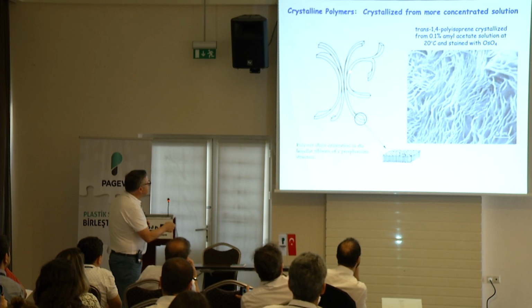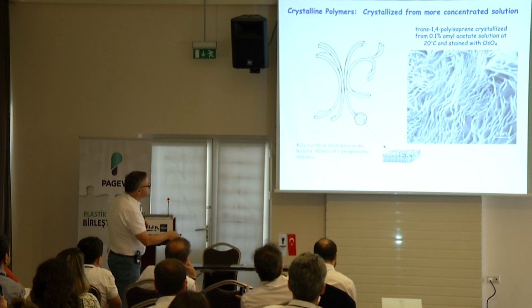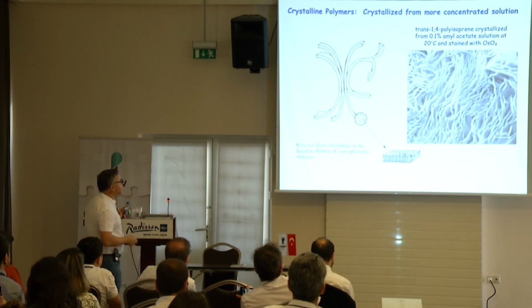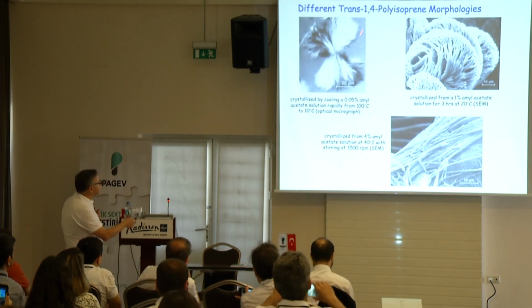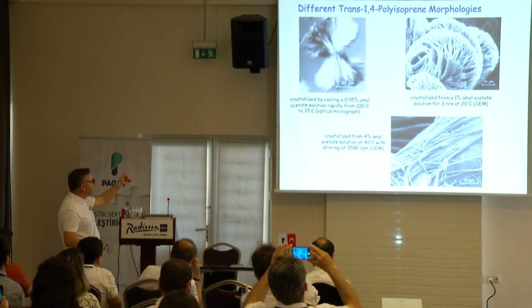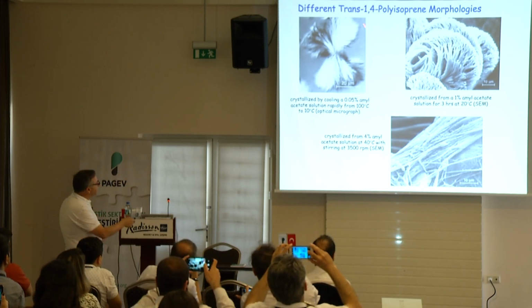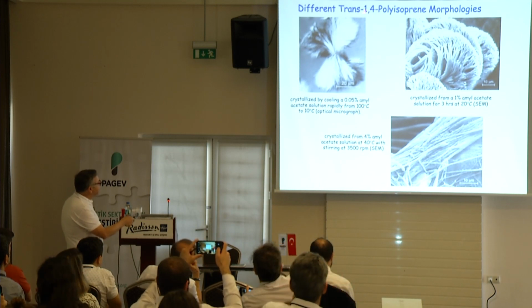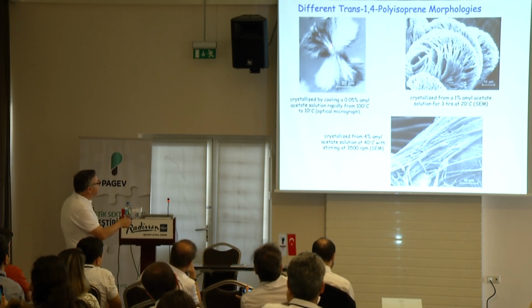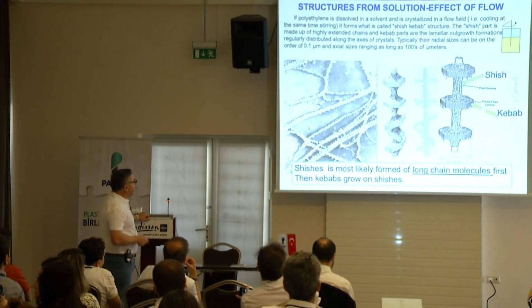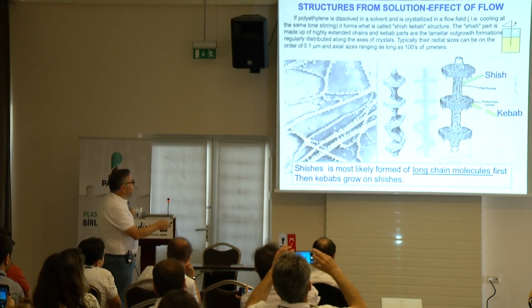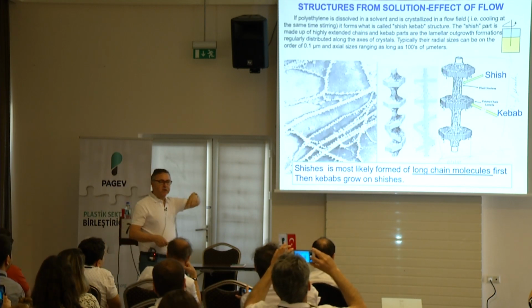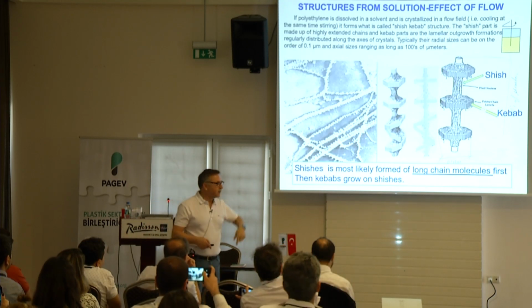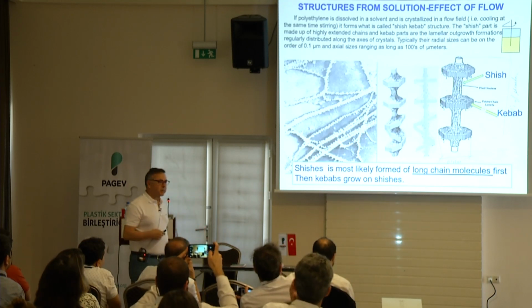So typically that's what happens. They form and they branch and they branch and they branch, and you kind of see it in the electron microscope. This is basically taken out. This is when you get more dense. Here's an example. You see, it looks more like a squeezed flower, a bouquet of flowers, literally like that. These are all these lamellar structures from various polymers. When you put the solution and with a simple stir, and you can actually do that in your laboratory, you just simply stir it, you will grow our famous shish kebabs.